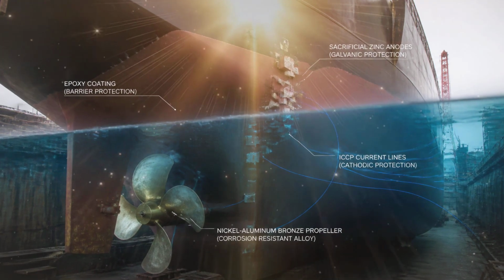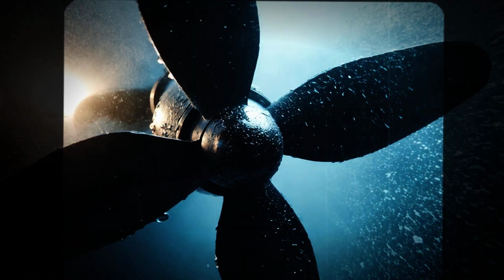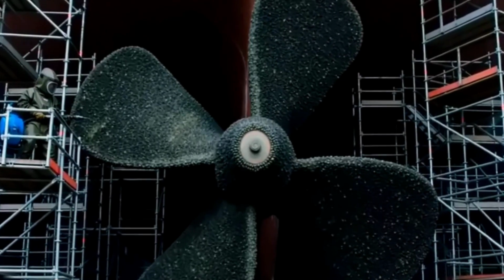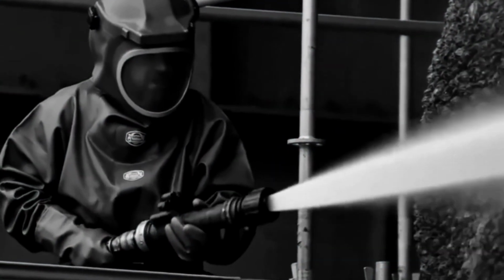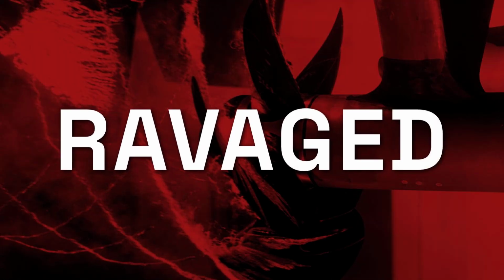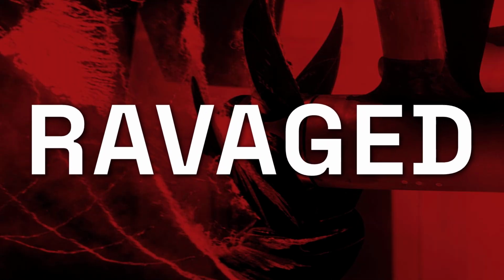Yet even this combined multi-layered defense has a hard physical limit. While anodes, electrical currents, and epoxy coatings successfully neutralize galvanic and uniform corrosion, they are completely powerless against the mechanical violence of cavitation erosion, tearing at the spinning blade tips.